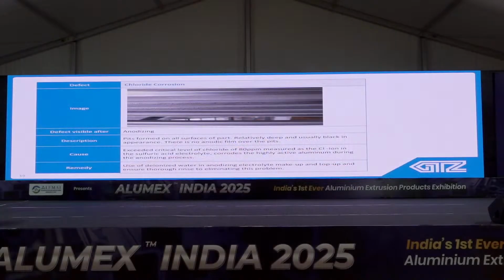Chloride corrosion: it can be visible after anodizing. Pitting formed on all surfaces. So how is it remedied? Use chloride-free water in the anodizing bath, and take care of any drag-in into the anodizing bath from the earlier stage.